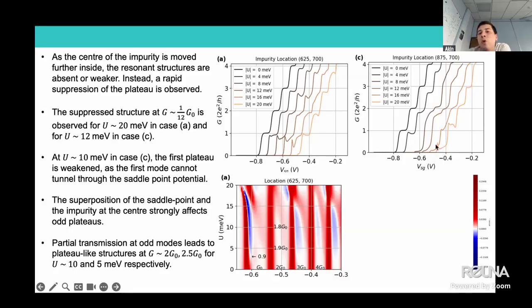Also, you can see not only resonances in these systems, but also shoulder-like structures in different places, so in these non-integer values. I think another interesting point to mention here between these simulations and the experimental data is series resistance. So in experimental data, there will be some series resistance in the system, and that needs to be carefully taken out. Here we know what our transmission probability is, so we can extract the conductance. In experimental data, you could maybe have these different plateau-like structures. Then, in non-integer values maybe, you should carefully understand what is the gap between each of those plateau-like structures to see if there's any suppression or not.